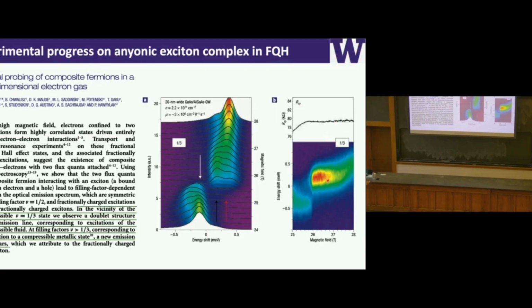And the bottom is a luminescence measurement. It's a color plot, so the vertical axis here is energy, and the horizontal axis is again the filling. What they show is that when the plateau starts to deviate away from this quantization, it means you start to have a mobile anyon in the system. And they observe a sharp change of the luminescence energy. Basically, a new feature appeared at lower energies.